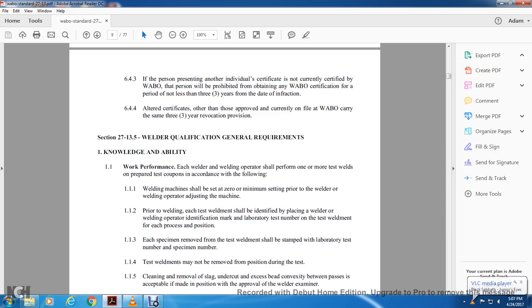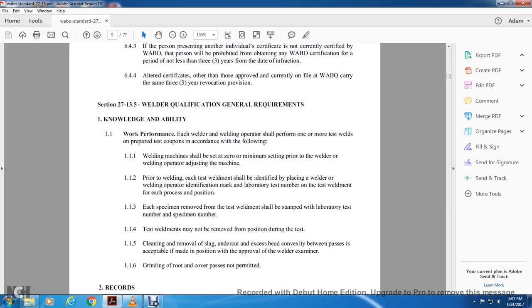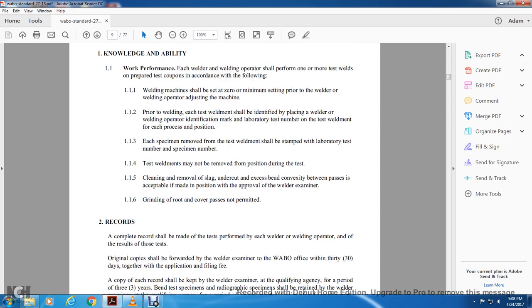Prior to welding, each test weldment shall be identified by placing the welder operator identification marker and laboratory test number on the test weldment, and on each of the process positions. Each of the specimens removed from the test weldment should be stamped with the laboratory test number and the specimen number. Test weldments may not be removed from position during the test. Cleaning and removing slag, undercut in excess of the bead or convexity between the passes is acceptable if made in position with approval of the welder examiner. Grinding off the root and cover pass is not permitted.